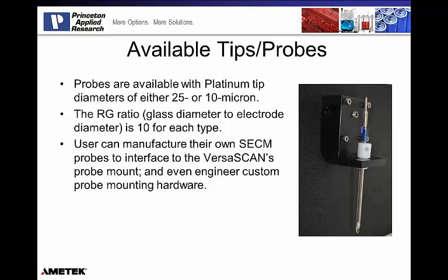So for example, if we took an RG ratio of 10, when we look at the very tip of the SECM probe, if it is a 25 micron probe, that defines the diameter of the platinum disc at the bottom of the probe. So that's a 25 micron disc at the bottom of the probe, and an RG ratio of 10 means that we have 10 times that amount of glass on either side. So it would be a 250 micron diameter glass, polished flush at the bottom, and then within that 250 micron glass at the bottom of the probe, a 25 micron platinum disc exists in the middle.